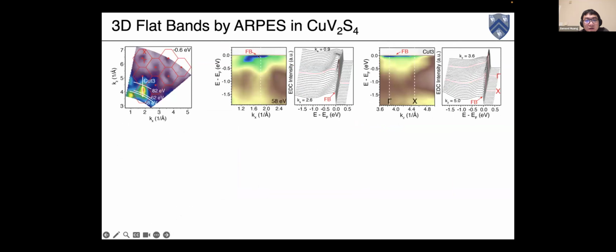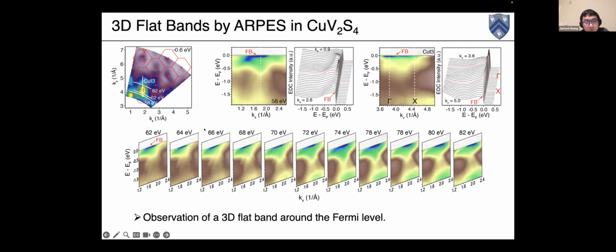If we use a relatively smaller photon energy to increase the vanadium photoionization cross sections, we can really see the vanadium flat bands that sit very close to the Fermi level, both in plane and out of plane. And we can do a very detailed photon energy scan that really shows this three-dimensional flat band. The flat band is actually pinned at the Fermi level by these orbital-selective electron correlations we mentioned before.